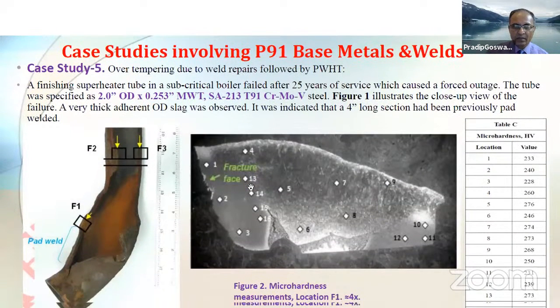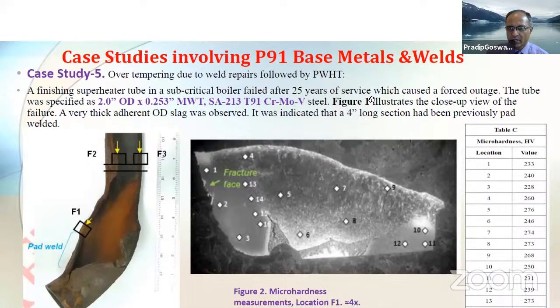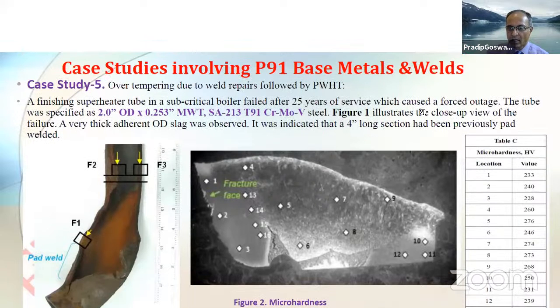This is another P91 failure. It says that a superheated tube in a subcritical boiler, not a supercritical boiler, failed after 25 years of service, which is fairly, I would say, it had done its own part, causing a forced outage. The tube was a grade 91 steel, which is a typical 2-inch OD and typically 5 millimeter or 6 millimeter of wall thickness.